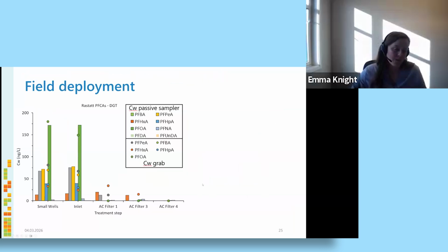So what does that look like when we back calculate the concentration in the passive sampler to an actual concentration in water? And how is that relative to the measured concentration from the grab sample? So as we can see here, this is when we've made the concentration in the passive sampler relative to the concentration in the water and not just mass accumulated. And what we're looking at is the bars, which are the passive sampler, versus the dots, which are the concentration from the grab sample in water.